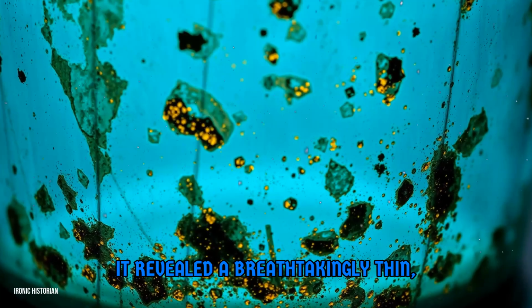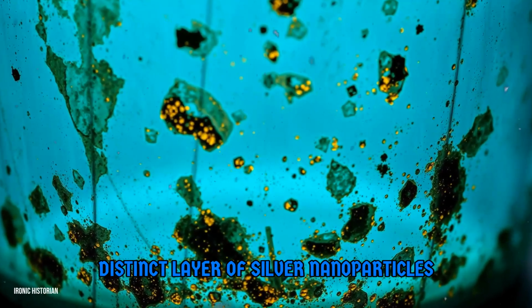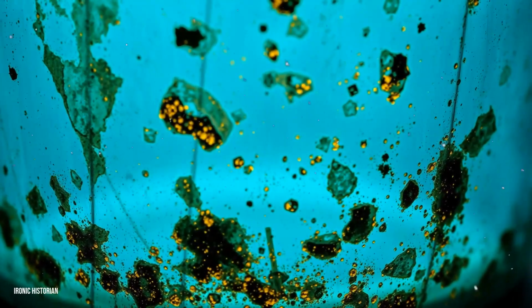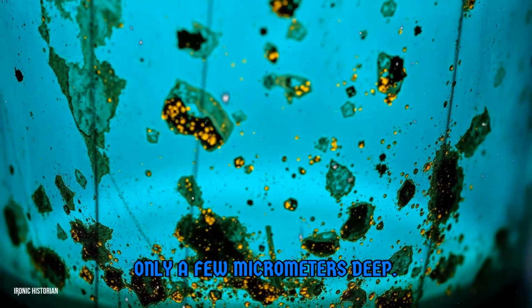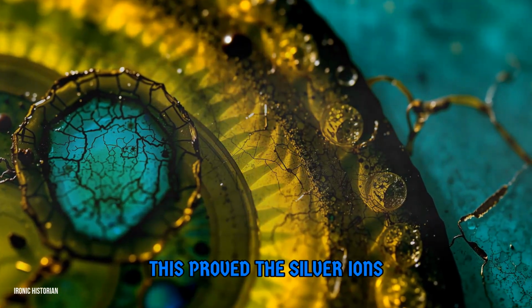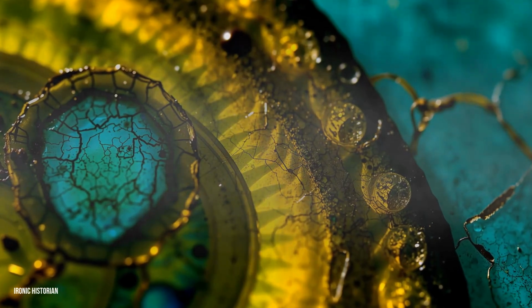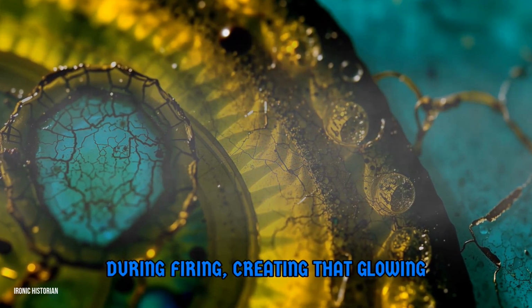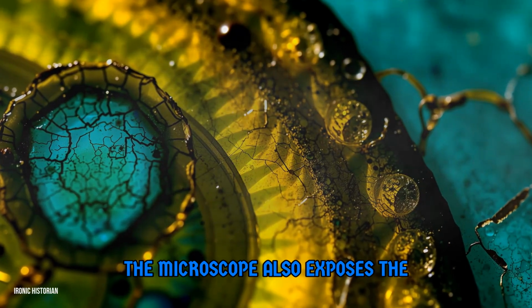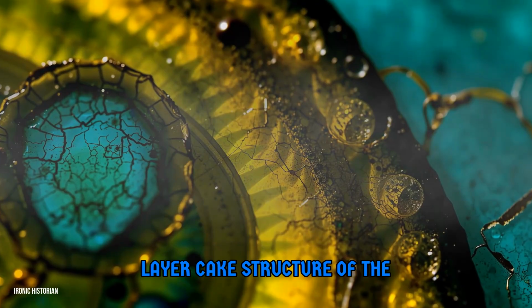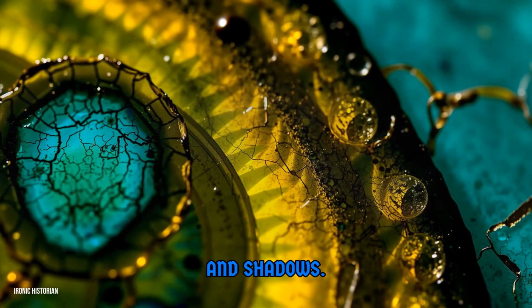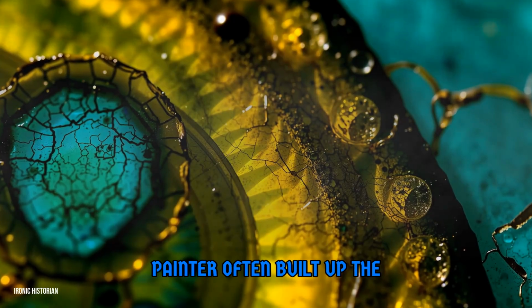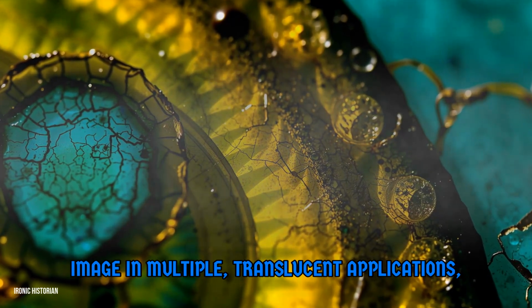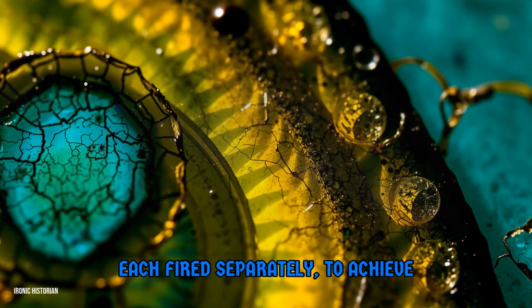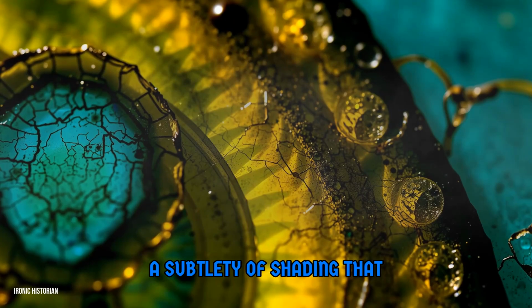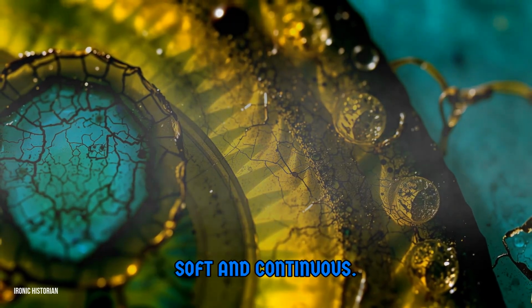It revealed a breathtakingly thin, distinct layer of silver nanoparticles embedded just beneath the glass surface, a permanent metallic touch only a few micrometers deep. This proved the silver ions did not just sit on the surface. They migrated into the glass during firing, creating that glowing color from within. The microscope also exposes the layer cake structure of the dark paint used for faces and shadows. It shows how the medieval painter often built up the image in multiple, translucent applications, each fired separately, to achieve a subtlety of shading that the naked eye perceives as soft and continuous.